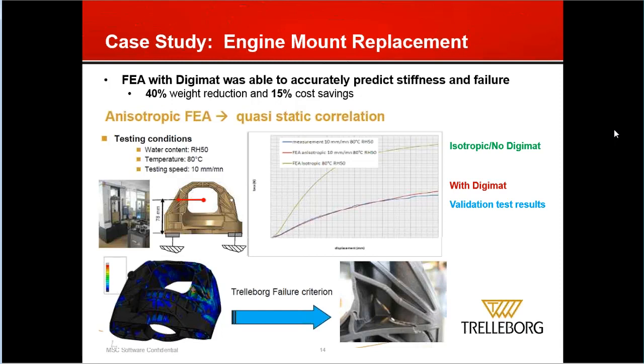And in addition, what you see below is that using one of Digimat's custom failure indicators, which monitors the material at a level below the composite, so looking at the matrix and the fibers more individually, they were able to get a very accurate prediction of where they should expect to see failure in this part. And while the stiffness may have been approachable with an isotropic model, predicting where and when the failure would occur is something that is extremely difficult with an isotropic approach, and someplace where Digimat really has a lot of added value. So that's a little more of a demonstration about why people are using Digimat.